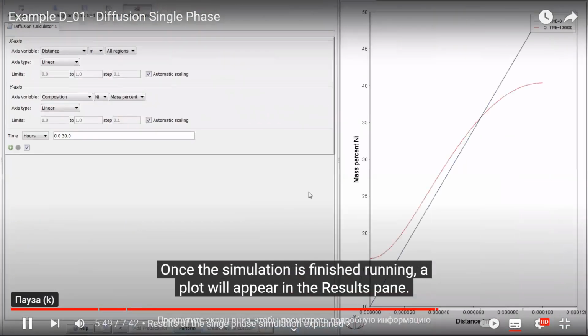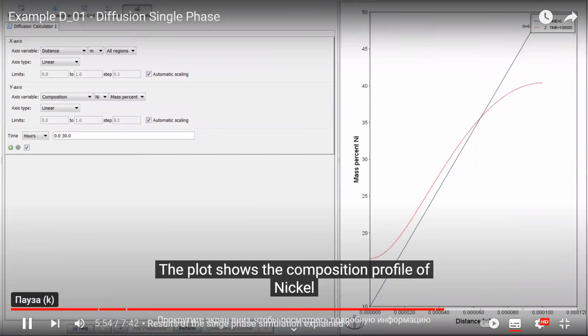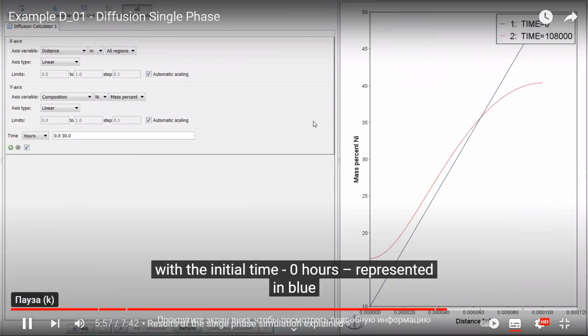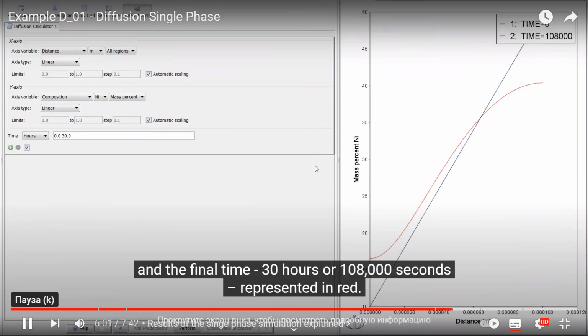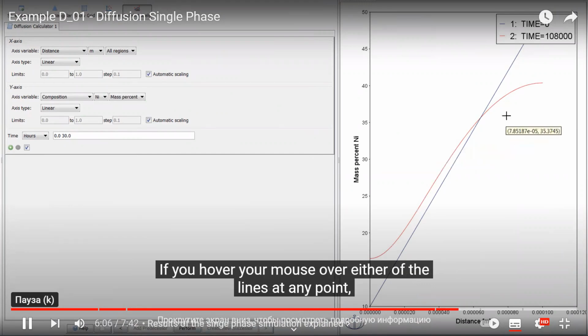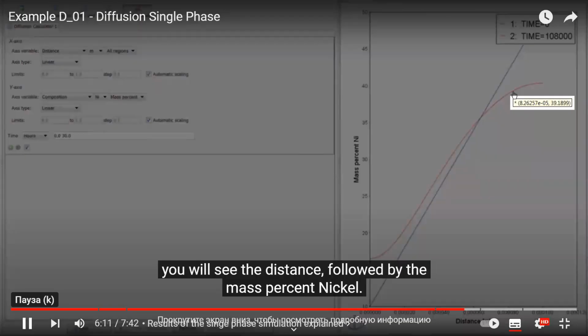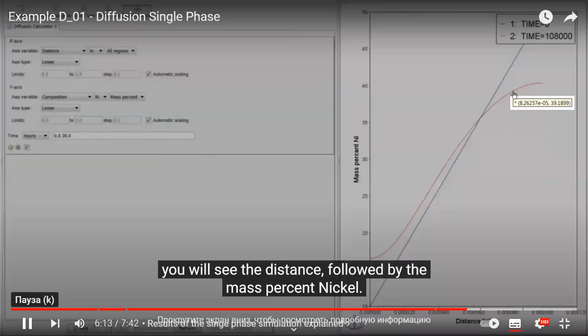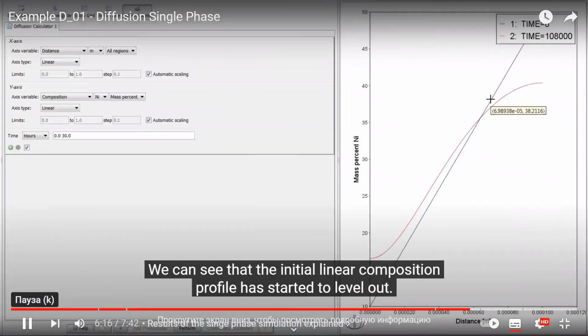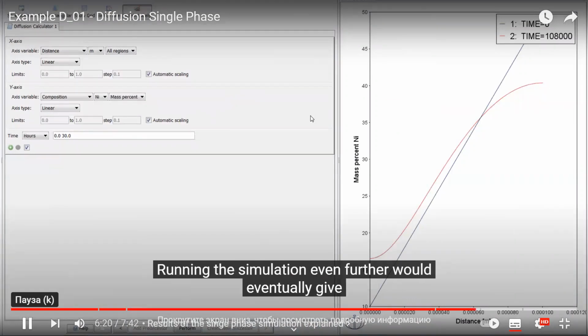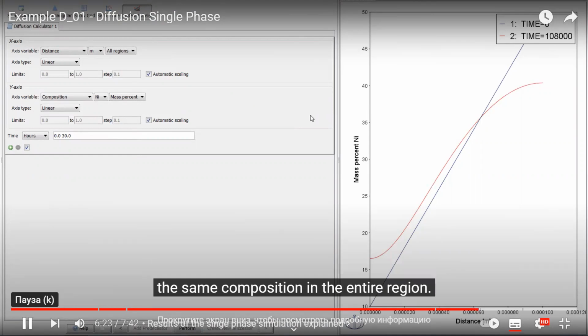Once the simulation is finished running, a plot will appear in the results pane. The plot shows the composition profile of nickel with an initial time, 0 hours, represented in blue, and the final time, 30 hours, or 108,000 seconds, represented in red. If you hover your mouse over either of the lines at any point, you will see the distance, followed by the mass% nickel. We can see that the initial linear composition profile has started to level out. Running the simulation even further would eventually give the same composition in the entire region.